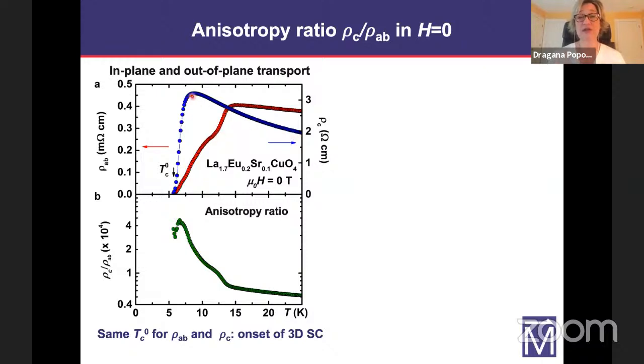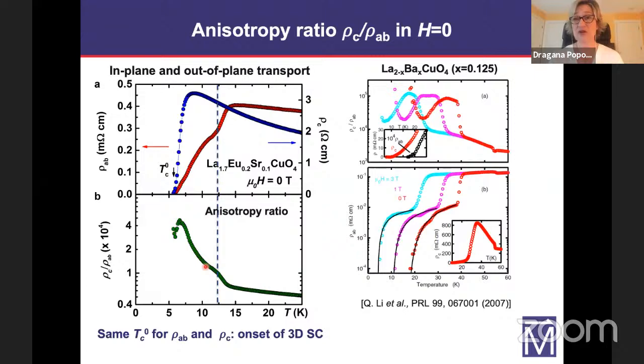However, the out-of-plane resistivity continues to increase, and they both go to zero at the same lower temperature. So in the place where the in-plane resistivity exhibits a drop, the anisotropy has this enhancement, this kind of bump. And this is actually the same thing that was observed in LBCO. This is the paper by John Tranquada's group that I discussed at the very beginning.